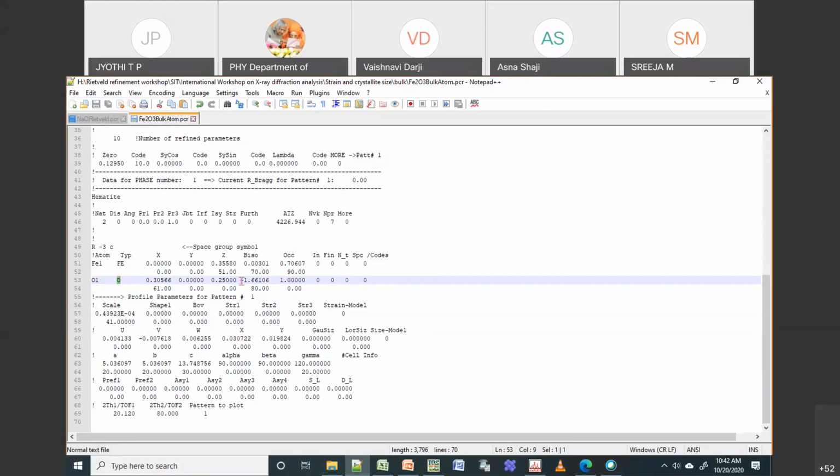Okay, even in case of BISO, whatever value you get here is not that highly reliable compared to what you get from neutron diffraction. If you do neutron diffraction, then you can do better refinement for very light elements like oxygen and hydrogen. So X-ray is not a really good tool for probing these occupancy things.